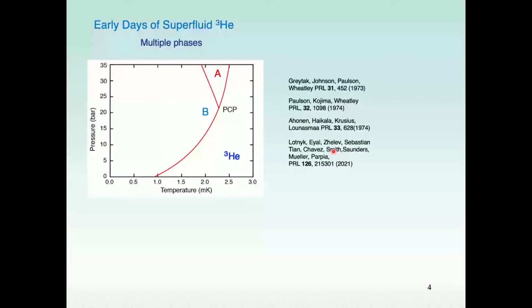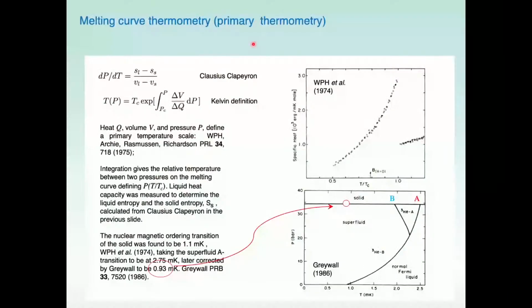So I want to come back to this challenge. That's the challenge of actually measuring the temperature. You can know from being on the melting curve, if it has a negative slope, that increasing the pressure decreases the temperature, but by how much? So at Cornell, it was prescribed that this Clausius-Clapeyron equation, which describes the slope of that equilibrium line, could be inverted and expressed in this way. And it's interesting to do so since measurements of the volume of the sample and measurements of the heat pulse which is inserted, and doing this measurement as a function of pressure between, say, 2 points, a reference point and pressure P, integrating gives the ratio of temperatures between those two corresponding points.